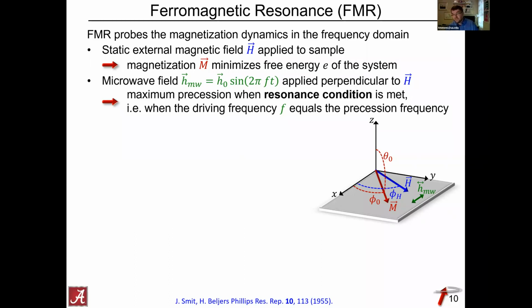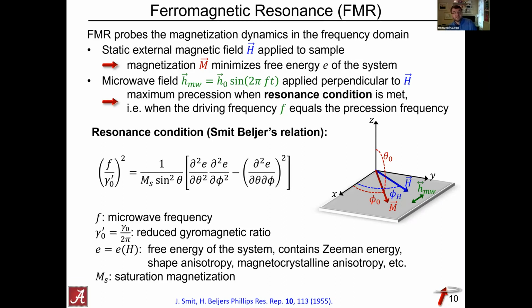And I always compare that with a kid on a swing that somebody tries to push. You're going to have a hard time pushing that kid if you don't hit the right frequency, the fundamental frequency of that pendulum. And this is the same here. You will only observe large-scale precession if you drive the system at the right frequency. So we need to look into what the resonance condition is. One way to write this down is the so-called Smit-Beljers relation. I don't want to go into all the details, but the resonance frequency is related to the second derivatives of the free energy of the system. And the free energy will contain the Zeeman energy, shape anisotropy, magnetocrystalline anisotropy, and so forth.